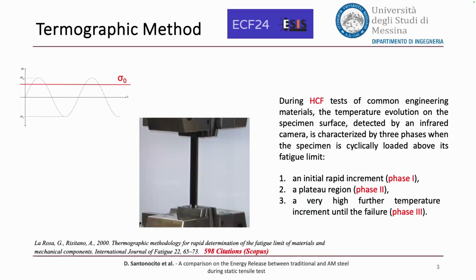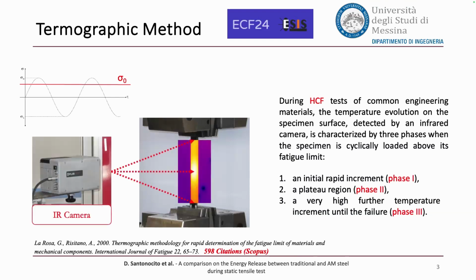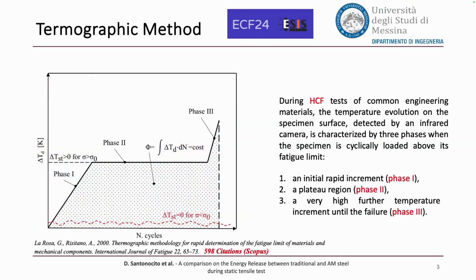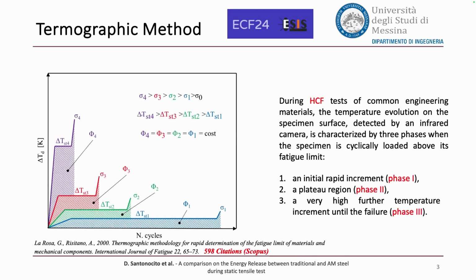So first of all, I want to introduce the thermographic method. During a high cycle fatigue test of common engineered materials, the temperature evolution of the specimen surface detected by an infrared camera is characterized by three phases. An initial rapid increment, then a plateau region, and then a very high further temperature increment until the failure. The more we increase the applied load, the more the temperature of stabilization will increase and the number of cycles will decrease, and the energy parameter will be constant.